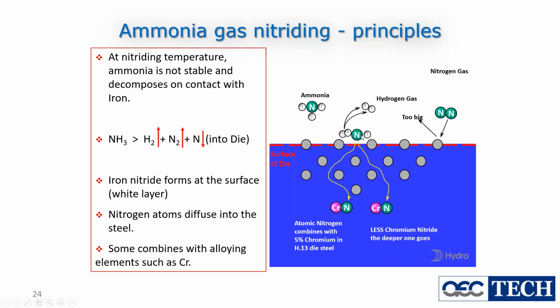Now this nitrogen atom is produced here on the top of our beautiful blue aluminum. I guess that's because it's hydro blue. But we make our nitrogen atom here. And some of them go out and join another one and become a nitrogen molecule and disappear off. But some of them start to go into the surface. About 5% of them will react with things like chromium and manganese and other elements in the steel to make hardened particles. And some of them will just go in there and disrupt the matrix and form this diffusion layer.